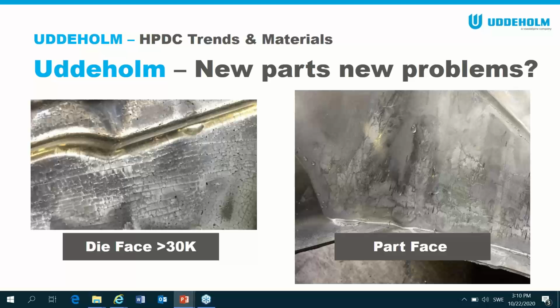If you look here, the picture on the left is a longitudinal bridge structure, which I saw in Europe. And you can see the heat checking here is pretty bad. This is the thermal fatigue damage that you see on these types of parts. This manufacturer is very good. They have excellent process control, some of the best I've seen in the world. And even they have problems. So this is an H11 type tool steel. It's 44 Rockwell, plus or minus 1. And you can see 30,000 shots just over.